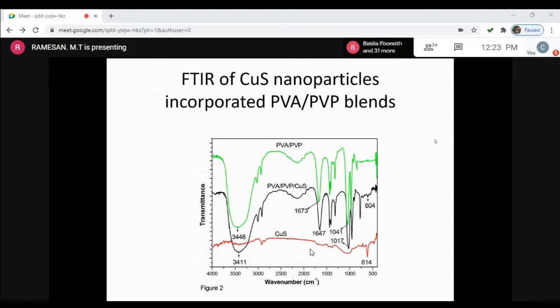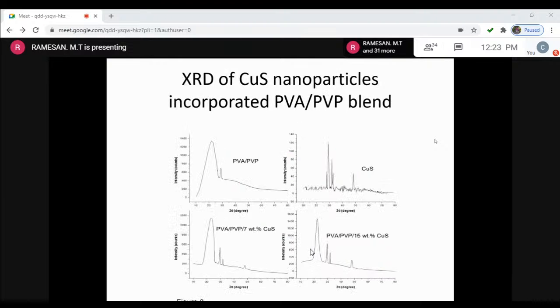In the FTIR spectra of the copper sulfide nanoparticle incorporated PVA PVP blend, you can see that the copper sulfide nanoparticle shows the CuS peak at 614, and it is slightly shifted to 604 in the PVA PVP copper sulfide system. This means that the copper sulfide nanoparticles are efficiently interpenetrated or incorporated into this PVA PVP blend. This is the XRD of CuS nanoparticle in PVP, and here also you can see the presence of the crystalline peak of copper sulfide in that system.